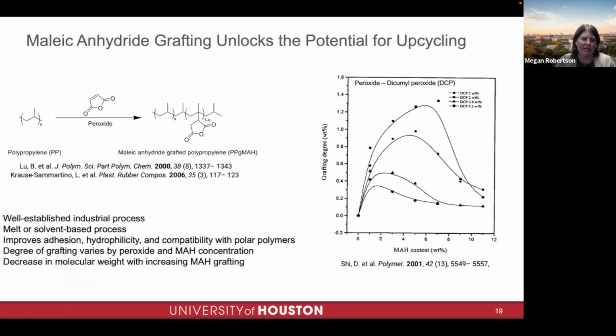Okay, so we relied on a functionalization route for polypropylene, which is actually very well established in industry, and that is the addition of maleic anhydride functional groups. In the presence of a peroxide, this can be done under melt extrusion. So it's a well-established process. We can vary the level of maleic anhydride grafting as well. And because polypropylene often undergoes chain scission, this process usually should reduce the molecular weight of the polypropylene. That's not a showstopper for us because we are going to take this functionalized polypropylene and then incorporate it into a cross-linked polymer through the formation of urethane bonds.